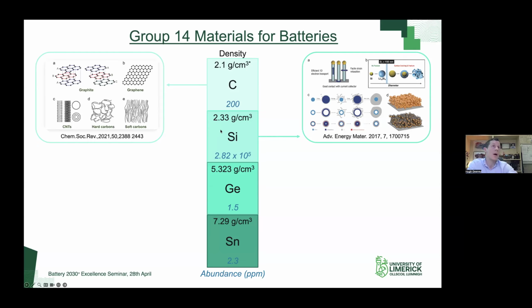As again, people are, I'm sure, very aware, these go through these lovely alloying mechanisms. So, for example, your fully alloyed silicon content here is up to Li15Si4 at room temperature. But because the silicon is accommodating so much lithium, we have significant volume expansion in that active material. So there's been all sorts of sophisticated material design approaches where people have looked at nanowires, for example, which are a system that I will discuss in good detail today.